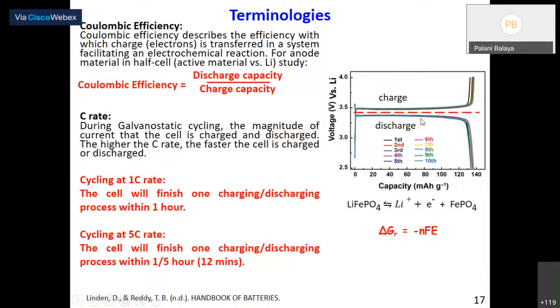So depending on the charge rate, if I do it very slowly, like 10 hours for charging and 10 hours for discharging, then the difference in potential, the so-called polarization, is very negligible, because as I told you, it goes as I square R. The lower the current, the I square R, which is the heat loss, is negligible. Whereas if I'm doing it at 5C, high current, by the way, theoretical capacity is 170 milliampere hour per gram. But in this particular case, I'm showing you 1C. That means taking 1 hour for charging. So my capacity is relatively low, 140 or slightly lower than that, because I'm doing it at a high C rate.